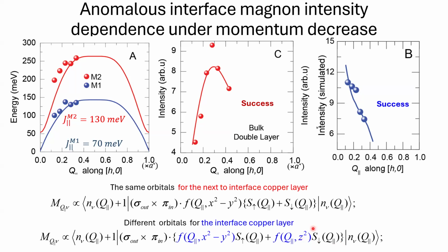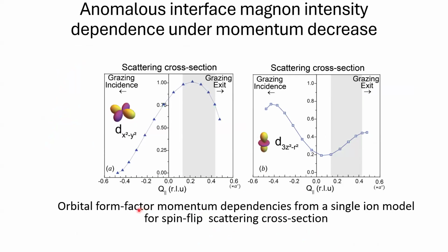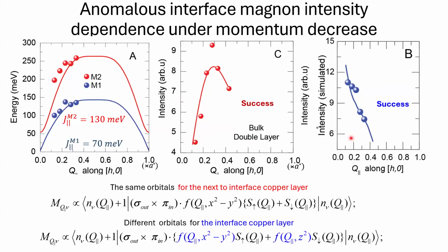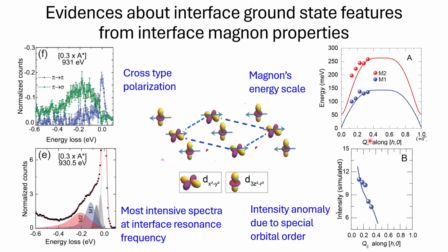If we apply this one, we can calculate the orbital form factor momentum dependence using the single ion model for spin scattering. Then we immediately get a very nice coincidence. So we have additional evidence that in our case we have such a specific orbital ordering. So we have four pieces of evidence for our restored orbital state at the interface copper oxygen 2 layer.